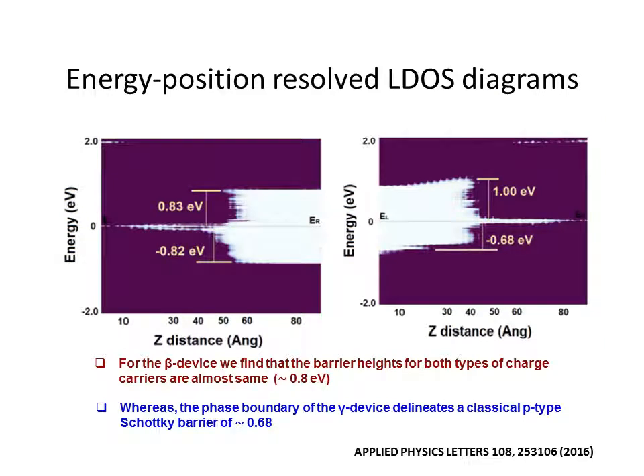Now, to investigate the charge carrier transfer through beta and gamma phase boundaries, we have converted the optimized heterostructures into two-port device structures. The length of the semi-infinite electrodes are taken as 5.75 angstrom and 5.53 angstrom formed extending the 1T' and 2H units, respectively. In order to calculate the transmission along the channel of the two-port devices, we use NEGF formalism along with the DFT calculation.